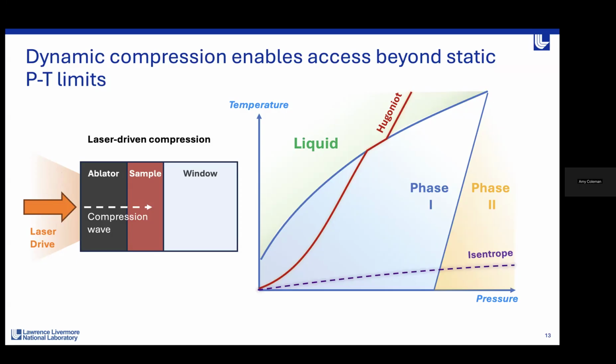And historically, there have been two main modes of doing this type of compression experiment, right? The first is shock compression. And when you shock a sample, you end up in a pressure state that is on a curve called the Hugoniot. And that's this red curve that I'm showing here on the phase diagram. Now, the Hugoniot is defined as a locus of states that are accessible via shock compression. And one thing that you'll notice about it on this phase diagram is it increases in temperature quite rapidly as it increases in pressure. So this is a very sharp shock compression.